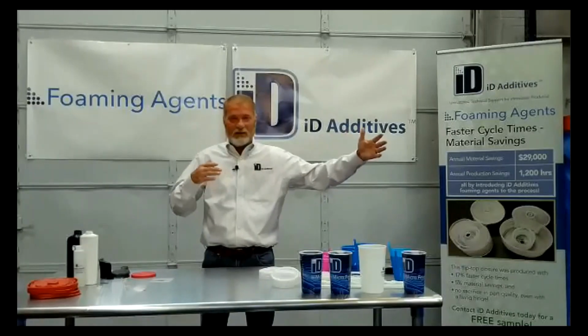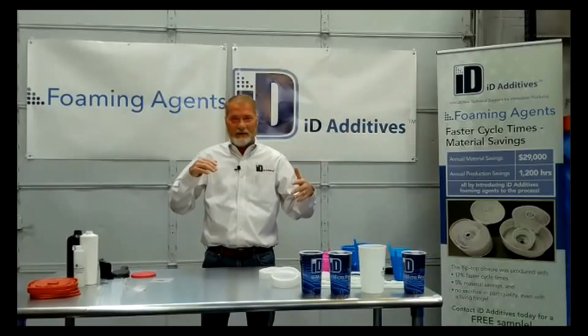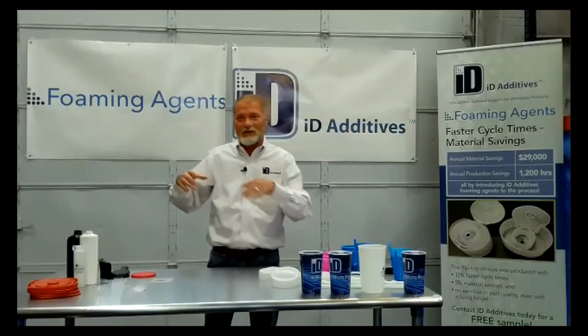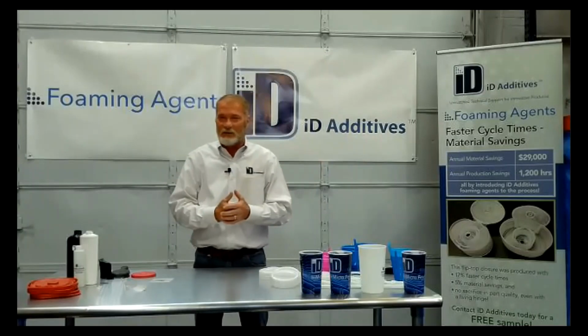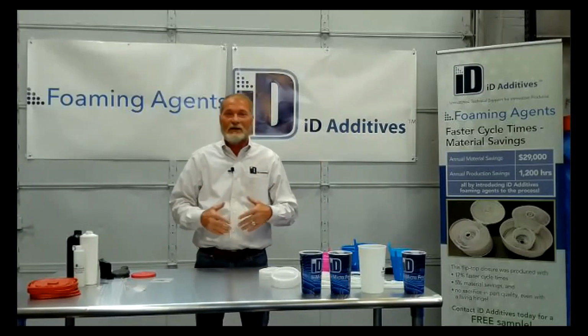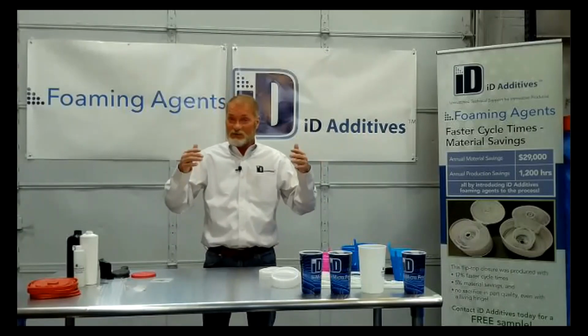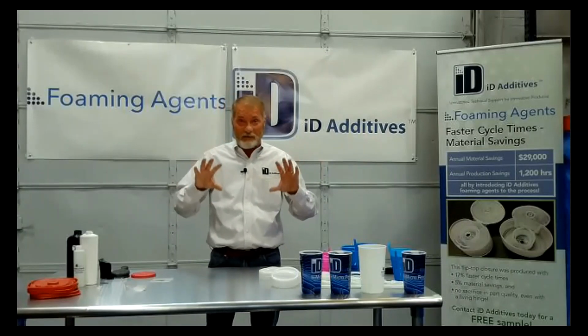If it's got a sprue in it, the mold will come out, and you won't have that drool because you're bringing those temperatures down. You hold it a little bit longer to settle things down. If it's a manifold system, you do the same thing with the tips, and you bring your manifold temperature down.